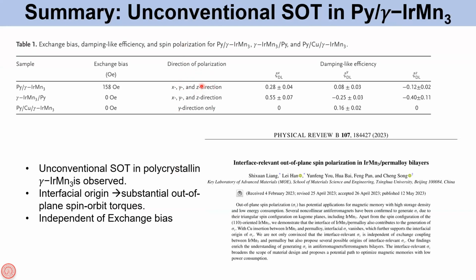What we see is that whenever the IrMn3 is in direct contact with the permalloy layer, we see a polarization, both out-of-plane polarization as well as X and Y polarization. Y is the conventional one, and that is observed in the copper case when the copper layer is there. In all other cases, we are seeing all the directions of polarization. And so this leads to the conclusion that there is a substantial out-of-plane torque that we are observing, and it is related to the interface.